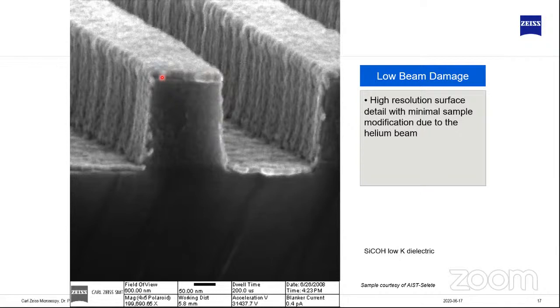What happens very often if you try to do that in an electron microscope, you observe some shrinkage or swelling of these structures under the electron beam. And to avoid the shrinking of these structures, you need to go to very low voltages like 500 volts, 400 volts, or sometimes even below. And the result of that is that we would lose resolution and we don't have an accurate measurement anymore.